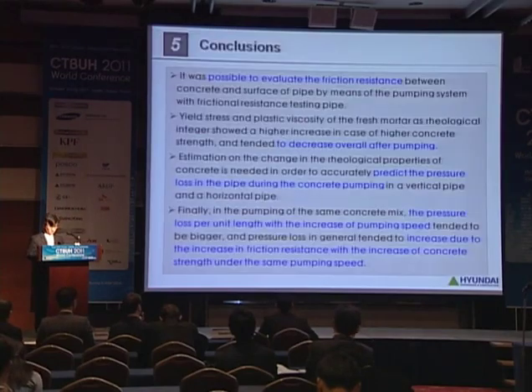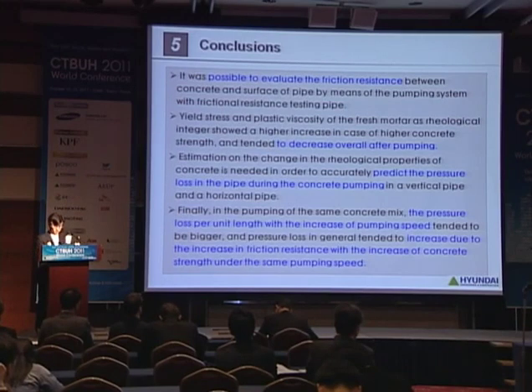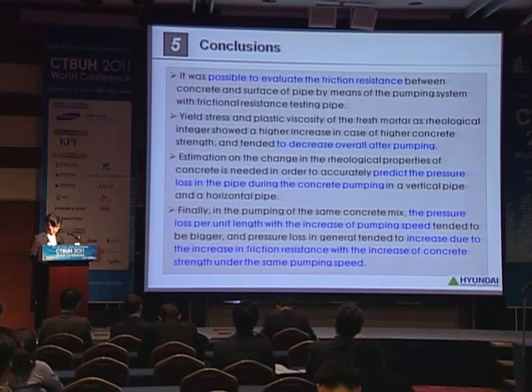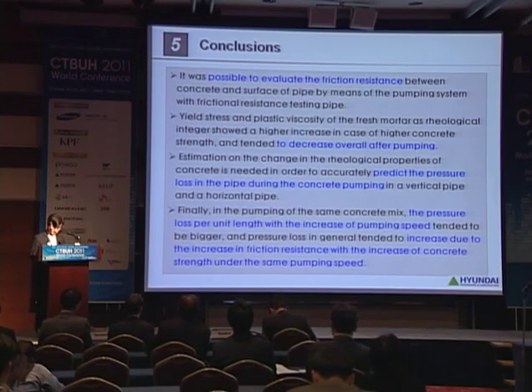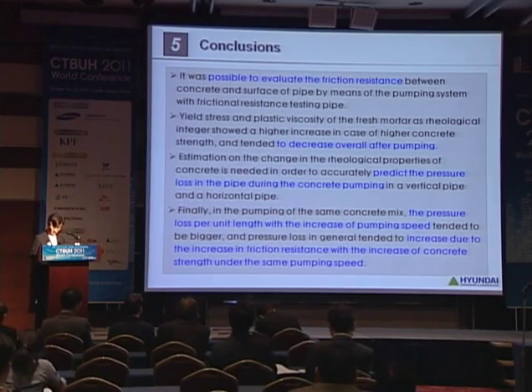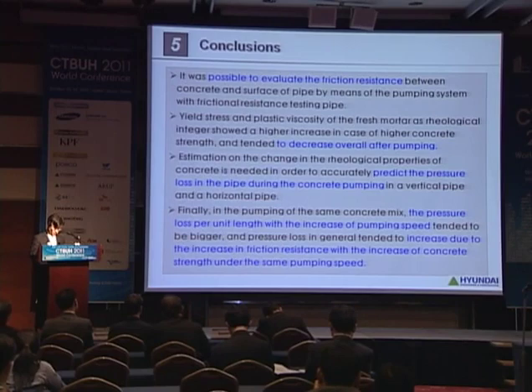Finally, conclusions. The conclusions of this study are as follows. It was possible to evaluate the friction resistance between concrete and the inner surface of the pipe by using the pumping evaluation system with friction resistance testing pipe. Next, yield stress and plastic viscosity of the fresh mortar showed a higher increase in case of higher concrete strength and tended to decrease overall after pumping. And estimation of the change in the rheological properties of concrete is needed in order to accurately predict the pressure loss in pipe during concrete pumping in a vertical pipe and a horizontal pipe.